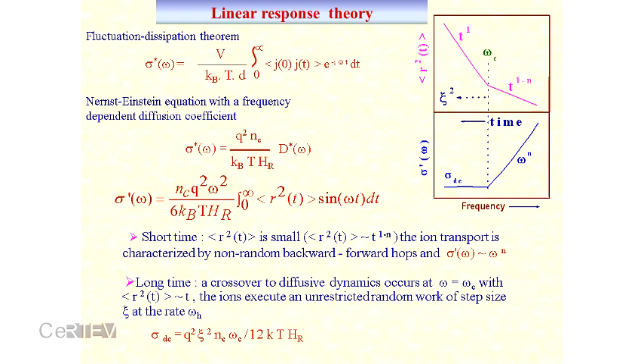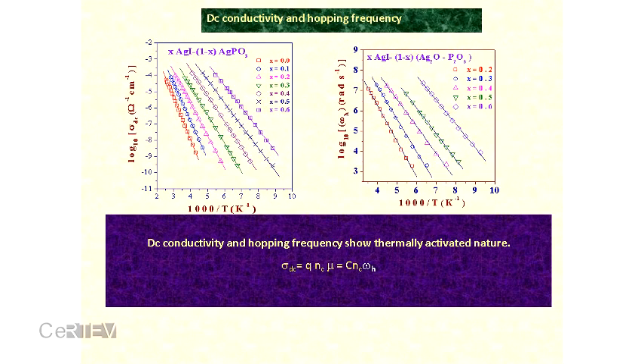After using this theory and our experimental spectra, we have calculated the DC conductivity and the crossover frequency. We can see that the DC conductivity is Arrhenius, the hopping frequency is also Arrhenius, and with the same activation energy. What does it mean? We have measured sigma experimentally with some activation energy, and we measure the hopping frequency with some activation energy; with the same activation energy for sigma and omega h, what about N C? This C is a constant. So if the activation energy is the same, then the charge carrier concentration has no activation energy, that is, it is independent of temperature. Let us see the result.